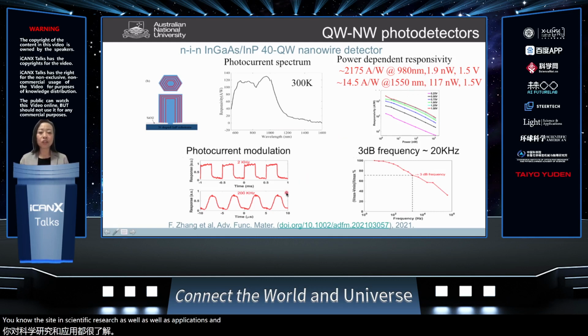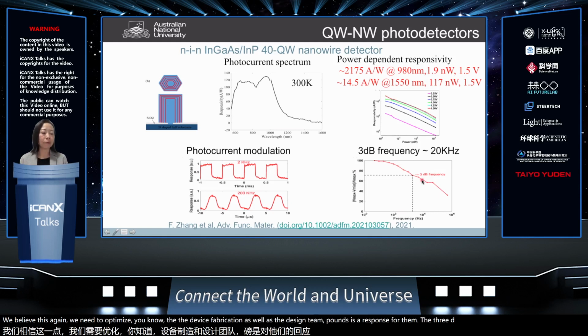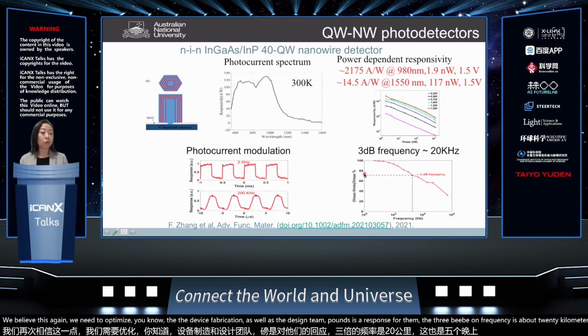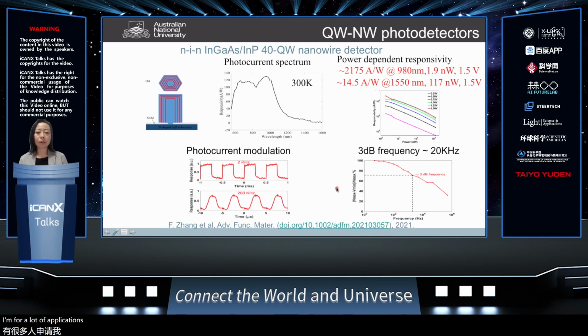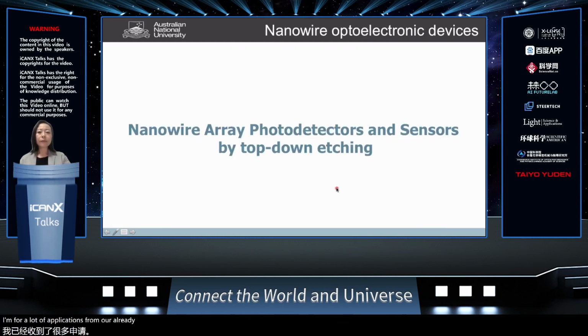We have also shown that we're able to modulate the photodetector at up to 200 kilohertz. Again, we need to optimize the device fabrication as well as the design to enhance this response, but the 3 dB frequency is about 20 kilohertz, which is quite nice already for a lot of applications. So I think I have about 5-6 minutes.